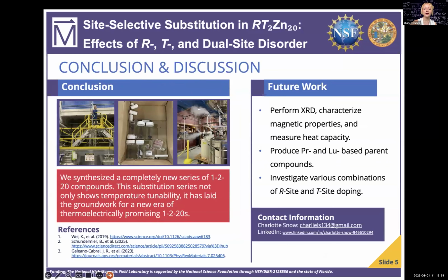So to conclude, we've created a completely new series of 1,2,20s that show temperature tunability, meaning we can adjust which elements go where to optimize them for either high or low temperature settings. As a next step, we'll study our samples using X-ray diffraction, take magnetic and heat capacity measurements, and we'll synthesize praseodymium and lutetium-based parent compounds, and we'll also investigate more R and T site combinations to improve upon our design.